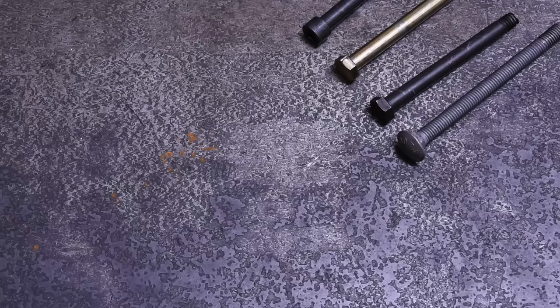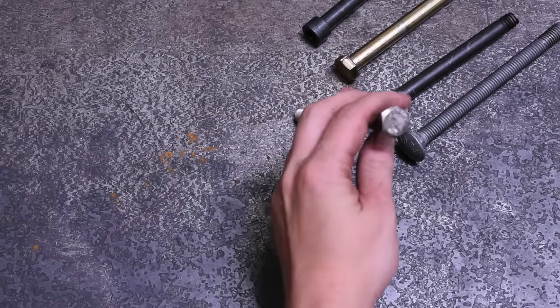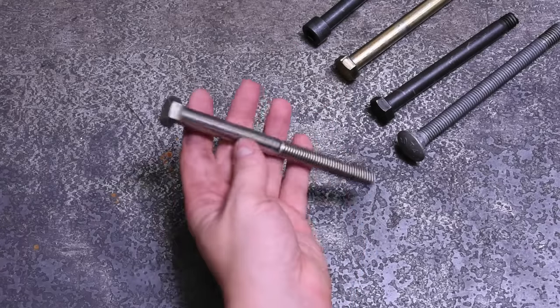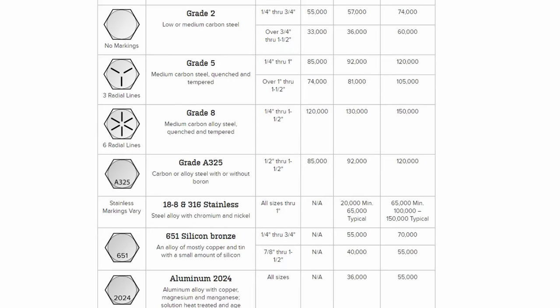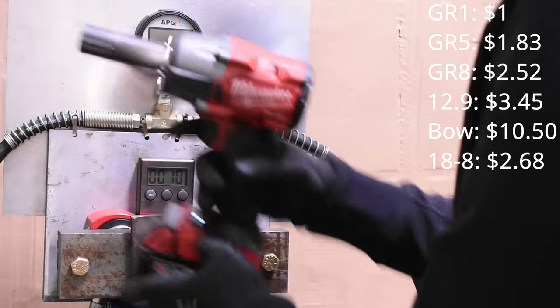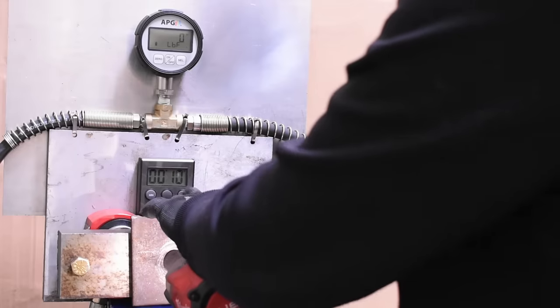So lastly we have stainless steel 18-8 grade bolts. This is a class of bolts made from usually 303 or 304 stainless, and are normally used for their corrosion resistance on boats and such. But there's a lot of wishy-washy info out there about these, people assuming because they are brighter and shiny and cost more they are stronger, which is ill-advised. But even spec sheets aren't all that specific about their strength, saying 65,000 psi minimum, but 100-150,000 psi typical, which is everywhere from a grade 2 to over grade 5. This one goes for $2.68 a piece, in bulk, which is more than a grade 8, but let's see how she does. Here's the M18 on high, let's just try and kill it already, shown in red on screen.